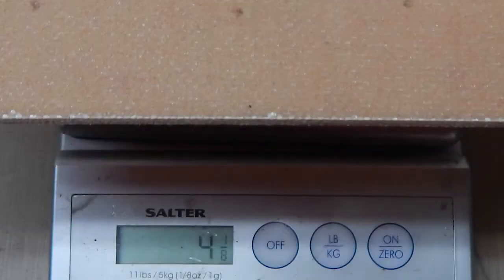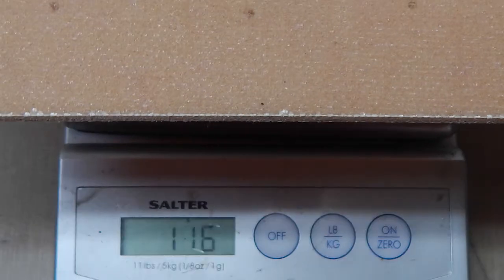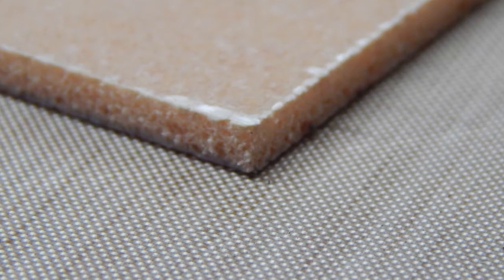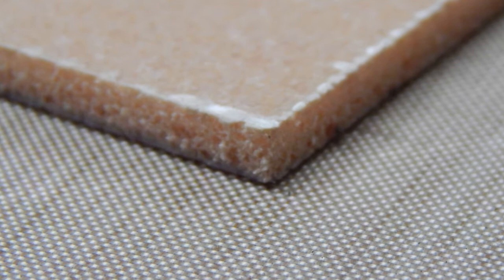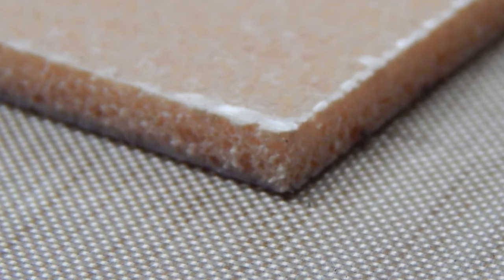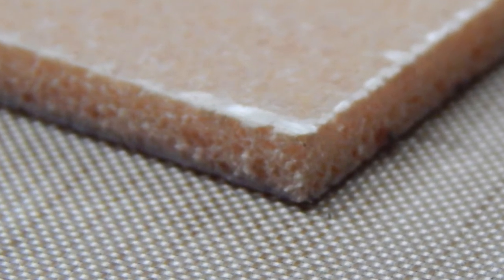But it'd be a handy type of panel. At 4 1/8 ounces per square foot, it's pretty light. That's 116 grams per square foot. And this is a picture close up of the peel ply side. You see the texture in there. And here's some of the pinholing on the mold face, which is not great. And up close of one of the corners showing the core texture.